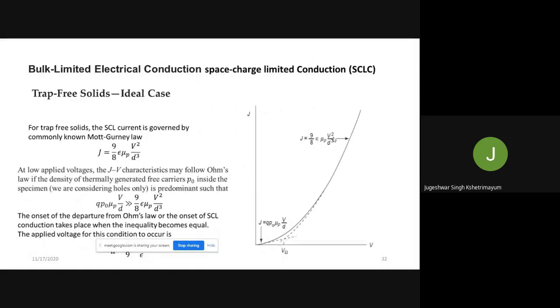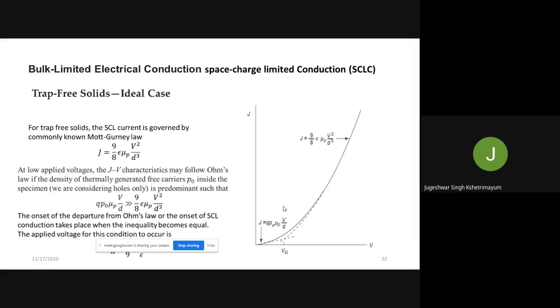Now from this ohmic contact to the space charge controlled region, there must be a transition. The transition is called the trap transition. Generally, an intermediate region is also observed between the ohmic and the space charge region, before the Child-Langmuir. In the region just above the ohmic voltage and below where space charge dominates, there is a transition region. What I have shown you here is this ohmic region, and this is the space charge region. This transition we will call the trap limited transition. This is what we are going to talk about.